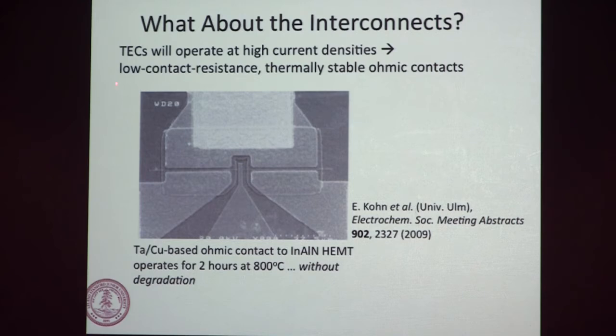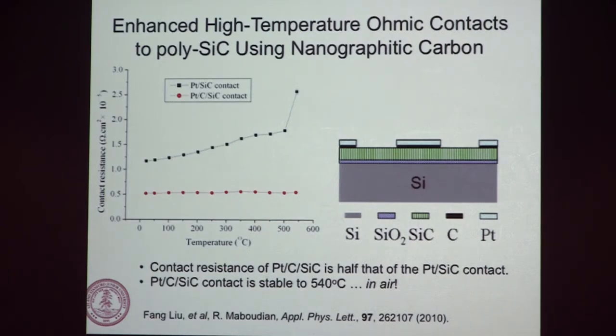Of course, we may have high current densities, and we have to have low resistance interconnects, but it's not something out of the question. In fact, my longtime collaborator, R. Maboudian, and her student, Fang Liu, who ended up at Analog designing MEMS up in the Boston area, worked on this, in Applied Physics Letters last year. This is the typical silicon carbide platinum contact running in air up to 500 degrees, and it's getting more resistive the hotter it gets. I forget how long this is running at 540. But then this red curve is their nanographitic carbon interface, again a nanostructured material that appears not to care at all. The furnace only goes to 540, but this is not in vacuum, this is in air. So I guess the takeaway would be our interconnects can go to these very high, harsh temperatures, and I think that'll open up a lot more applications than thermionics.